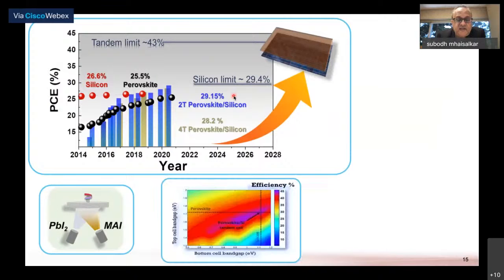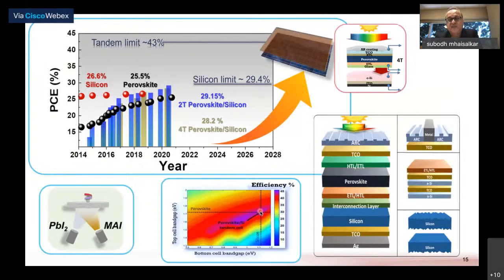The efficiency needs to be maximized by choosing the right material sets for the perovskites, where the band gap of the perovskite has a huge impact. So the band gap of the perovskites and the band gap of the silicon need to be properly chosen in order to maximize the performance of these devices. So here we work on both the 2-terminal as well as 4-terminal solar cells, and the challenges in each one of them is quite different.